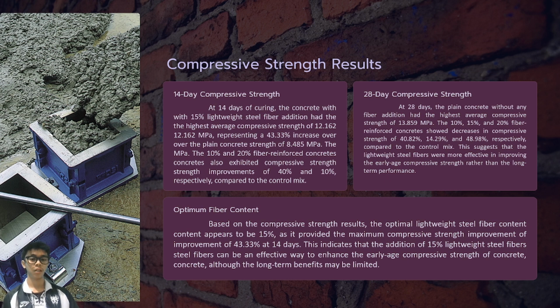Optimum fiber content. Based on the compressive strength results, the optimal lightweight steel fiber content appears to be 15%, as it provides the maximum compressive strength improvement of 43.33% at 14 days. This indicates that the addition of 15% lightweight steel fiber can be an effective way to enhance the early age compressive strength of concrete, although the long-term benefit may be limited.